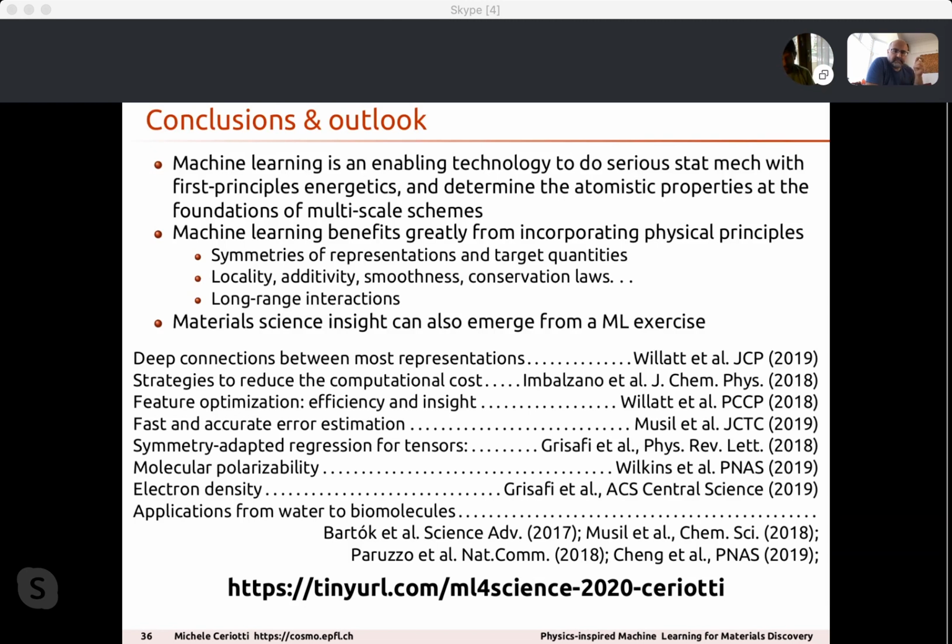For instance, something that we have been doing, so I'm kind of a pragmatist. If you want to study a really complicated system, for instance, we are studying some homogeneous catalysis where we have acid and hydrogen peroxide in a phenol solution, it's very hard to collect enough reference calculations to be able to build a machine learning model that is stable. So what we are doing is using the DFTB as a baseline. And the point is that the DFTB is kind of expensive. It's cheaper than the DFT, but it's still much more expensive than the machine learning model. And so you can do multiple time stepping. So I actually think that machine learning is beautifully suited to molecular dynamics. You can really combine a lot of the tricks of the trade of molecular dynamics with these machine learning schemes, and it brings you very, very far.